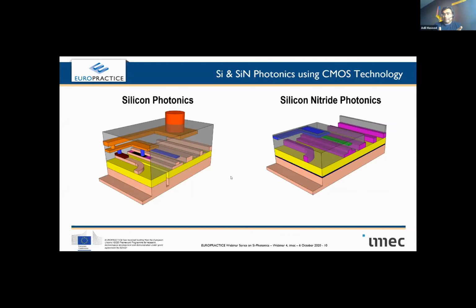So typically, you start with a silicon wafer, and that is not enough. It needs to have either an oxide deposition so that you can further deposit silicon nitride, or have somehow crystallized silicon on top of it, so that you can create this envelope of high index, low index contrast material for waveguiding. So as you can see in both the images, it's not really a wafer, but a slice and 3D cross section of what a section with waveguides and all would be.